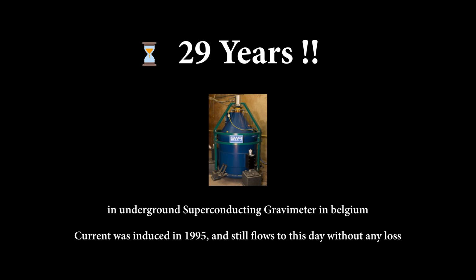Today, we have had currents persisting in the superconducting state for about 29 years without any measurable loss. If there was still a decay of current due to some super small resistance, then for the current decay to escape this kind of experimental observation, it would have to be so slow that the current decay time would have to be longer than the age of the universe. Persistent current, ever since Onnes' experiments in 1914, is the ultimate proof for the actual zero resistance of the superconducting state of matter.